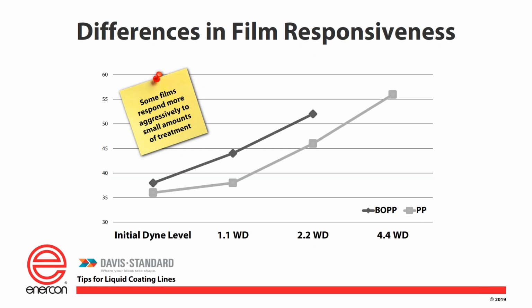So again, really a good example here where we had BOPP versus polypropylene, and you apply different watt densities and you don't get the same dyne level results, right? It's really the same category. Depending on the film structure, additive loading, age, and so forth, some films respond better to more aggressive amounts of corona treatment. Like in this particular case, watt density of 2.2 gave us one result with one film, gave us a different result with another film. And as I go up in power here, at a watt density of 4.5 almost, I still ended up getting some benefit. But on the other hand, on the other film, I got nothing. It sort of plateaued out. So the film, folks, the film makes a huge difference in terms of the ability for you to convert it accurately and effectively. Next slide.